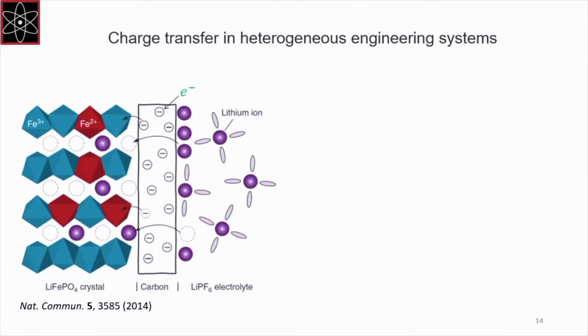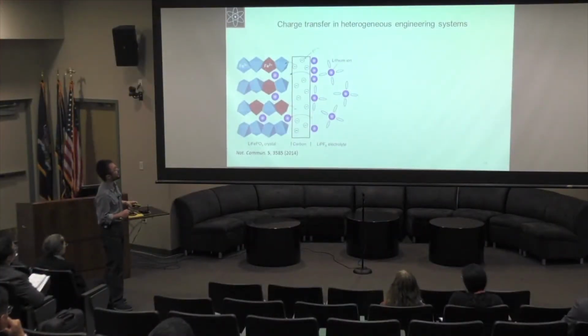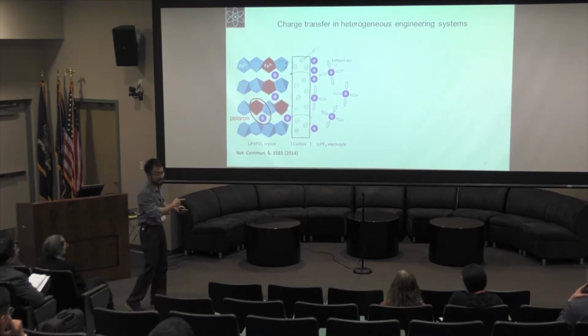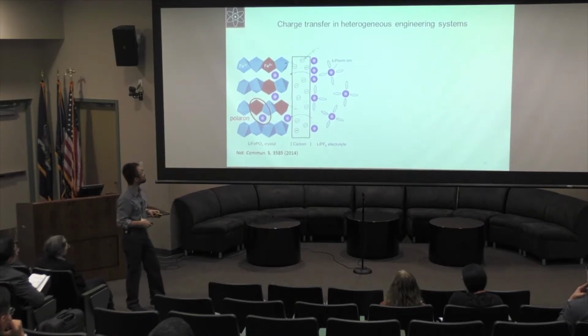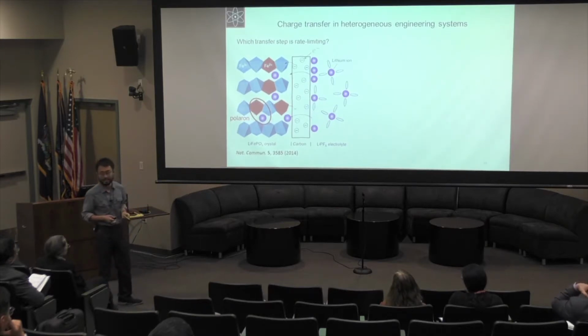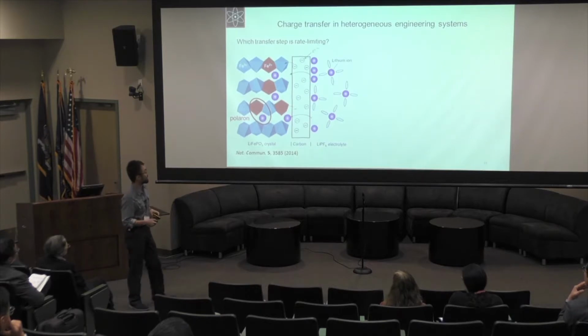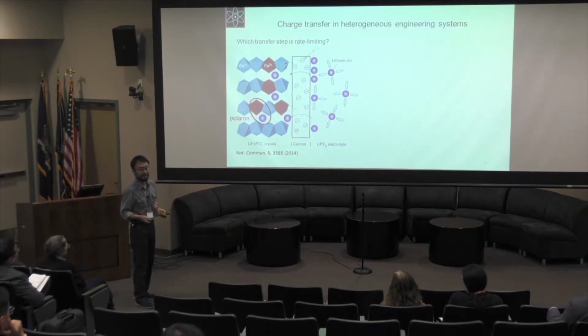actual devices. For example, in the charging of iron phosphate with lithium, one applies a negative potential to some carbon overcoating, and that would drive, say, the migration of positive lithium ions into the lattice, and then the electron can then jump to an iron 3 to make an iron 2. And the pair that's formed, like there are several here that are depicted, is called a polaron, and that thing can migrate into the lattice. So obviously, that's a very complex multi-step process. So the question is, which transfer step is actually the rate-limiting one? I'm not in the field, but just from reading the literature, it seems like there's a debate in the field as to whether it's lithium migration or electron transfer that constitutes the rate-limiting step.